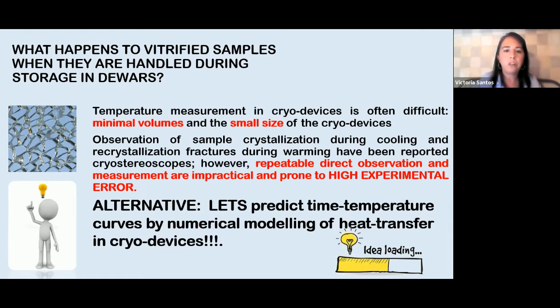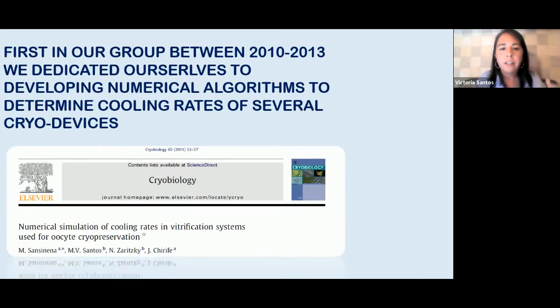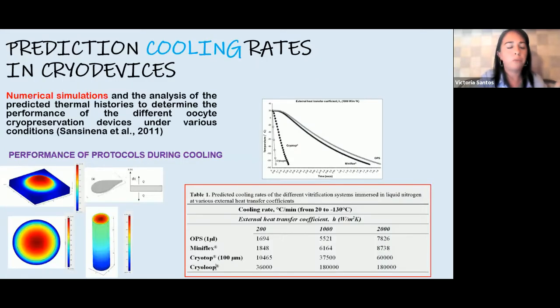So what are the alternatives? Well, we can predict time-temperature curves by numerical modeling of the heat transfer in these cryo devices. And we did that in our group, but we did it for cooling rates first. So we found the performance of each cryo device, for Cryotip, Cryotop, Cryoloop, etc. And we found the cooling rate and the performance for each of these devices.